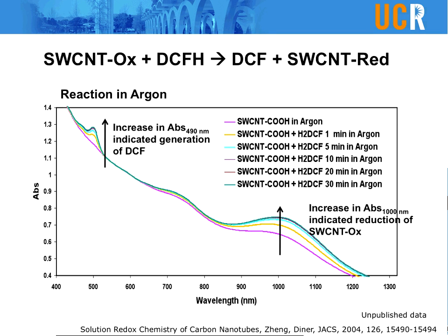This phenomenon is more obvious in single-walled nanotube modified by carboxyl group, because when it's manufactured, the carboxyl group is added by oxidizing the carbon nanotube in strong acid solution. That process actually introduces what we call oxidative single-walled nanotube, or single-walled nanotube acting as the oxidizing agent.